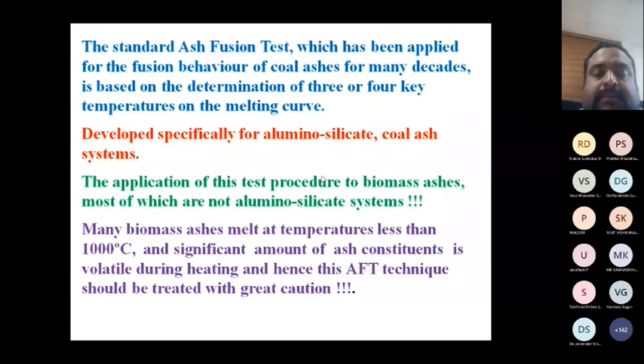Many biomass ashes melt at temperatures less than 1000 degrees. Another important parameter: most of the coal ashes melt at around 1200, 1300, 1400. Here, many of the biomass ashes melt at temperatures less than 1000 degrees, and a significant amount of ash constituents is highly volatile also. We have seen that a significant portion of the inorganics goes off as volatile. So the heating and hence the AFT technique should be treated with great caution. When you are doing AFT for biomass ash, something is volatile, there is no melting and all. So adaptation of the AFT technique for biomass must be done with great caution.